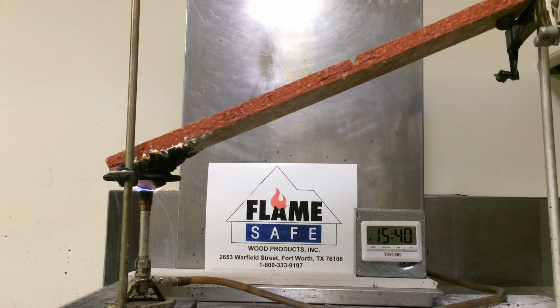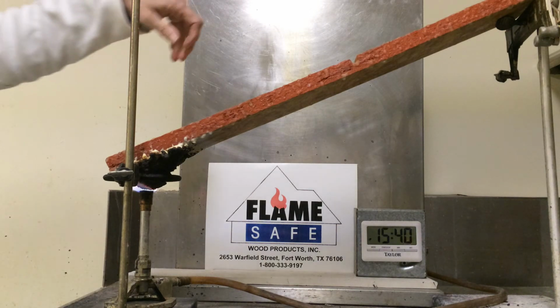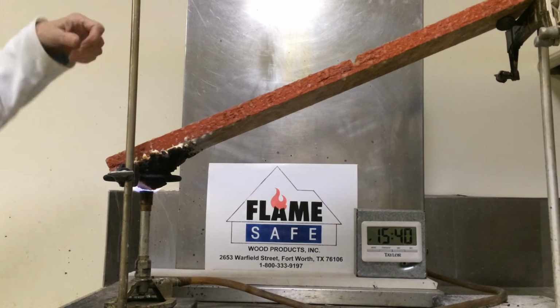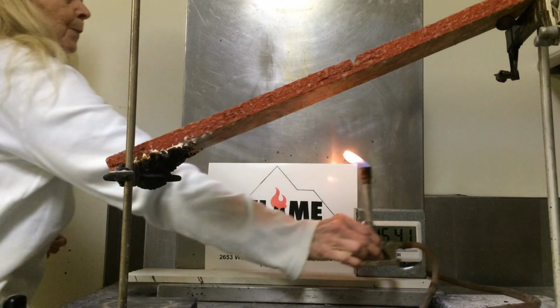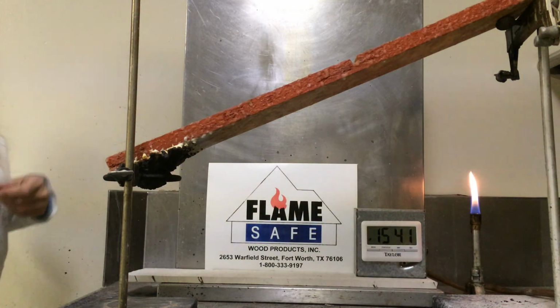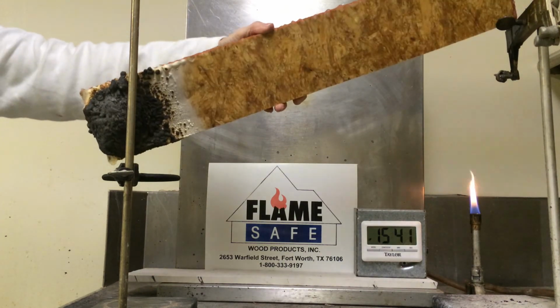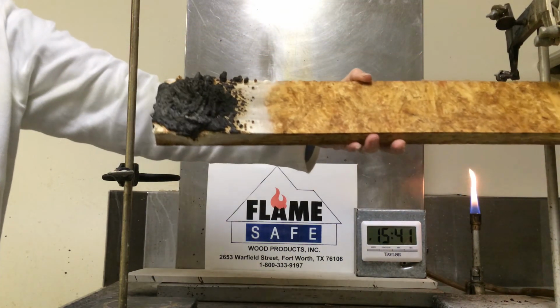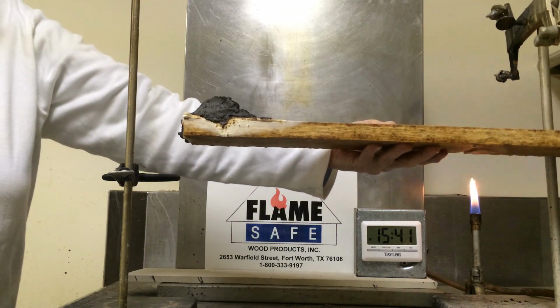We are going to continue this test for another minute, which will bring it to three times what the standard actually requires in this test. At this point, if you'll take note, the intumescent has expanded to within 1/8 of an inch from the top of the burner, completely blocking the flame. At this point, we're going to remove the Bunsen burner from underneath the specimen and rotate the specimen so that you can visualize the expansion.